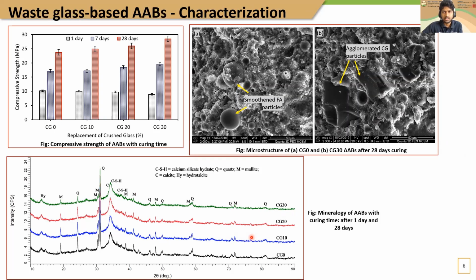Let's check the properties of waste glass incorporated alkali-activated binders. This slide shows the strength, microstructure, and mineralogy results of waste glass incorporated fly ash slag alkali-activated binders after different curing times. According to the results, the alkali-activated binder shows sufficient compressive strength, around 30 megapascal after 28 days, and a denser microstructure with increase in replacement of waste glass. It also showed fewer unreacted minerals of fly ash and slag, which we used as raw materials, in the hardened phase with the curing time. Therefore, these results confirm that waste glass would be a better alternative as a mineral precursor for one-part alkali-activated binders.